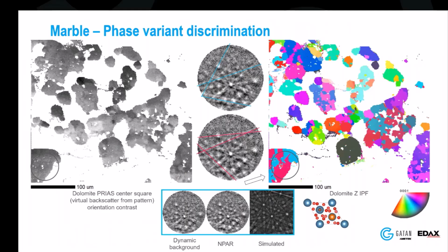We can see it is now basically this domain structure of these two orientations. And if you look down here, you see the very minor differences between these two patterns. This right here is the blue orientation. This right here is this reddish-pink orientation. You can see that most of the lines are shared between these two. So for the Hough to get consistent indexing, it needs to find the lines that these two do not share.